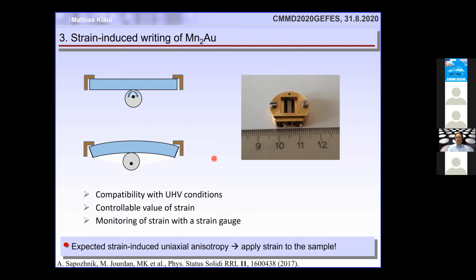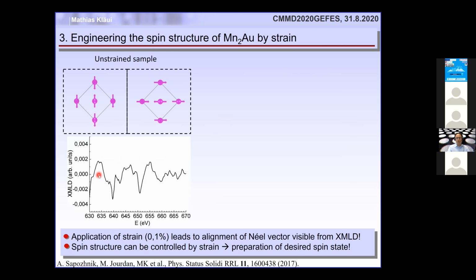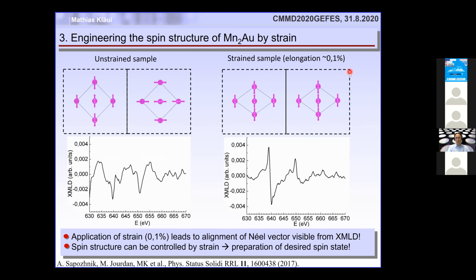So one option is to apply strain in order to generate anisotropies, because I told you that these anisotropies can be quite large due to the large magnetoelastic coupling. And so here we built a medieval torture device for samples, where we put a sample in here, and then we use the screws to tighten the sample until it confesses or it breaks. And actually it does confess, because as grown, we see a small signal, but when we strain the sample just by 0.1%, we can indeed get an alignment of the Néel vector in the direction of a uniaxial easy axis that is induced by the strain.